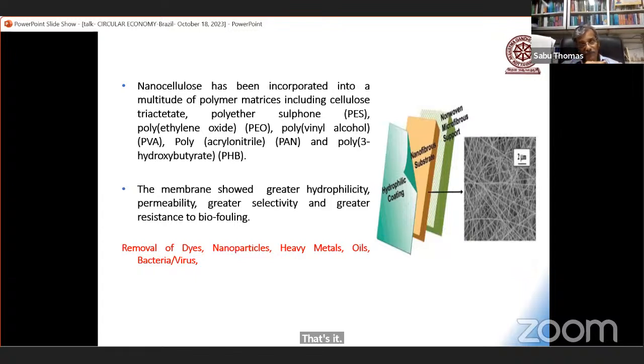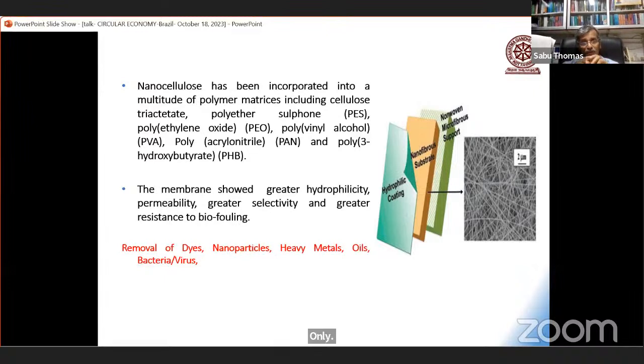So I'm going to show you what we have done, what my research group has done. If you look at the commercial water filtration cartridge, they are not very efficient. Most of the cartridges are made of bilayers. The bottom layer is mostly polyacrylonitrile, over which you have a PVDF, polyvinylidene fluoride. We found that commercial filters are not very efficient.